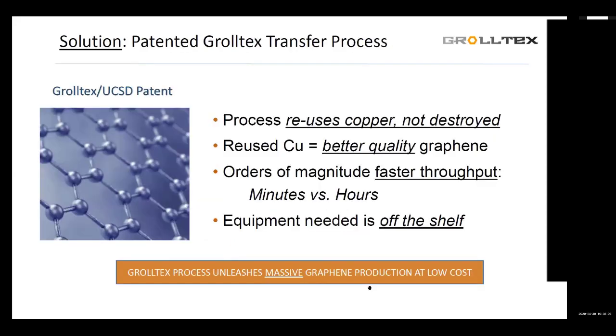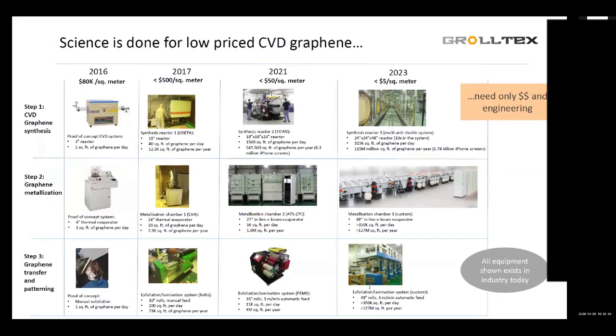So we have a patented process to remove graphene from copper and not destroy copper at all. We reuse the copper growth substrate, and as it turns out, the more times you use the same piece of copper, the better and better quality graphene you get. Our process can be done on a roll-to-roll basis, meaning it can be done in minutes versus the sometimes hours it takes to acid etch copper. And the equipment it takes to do our process is off the shelf. It exists in industry today, very well understood processes. This is kind of what it looks like.